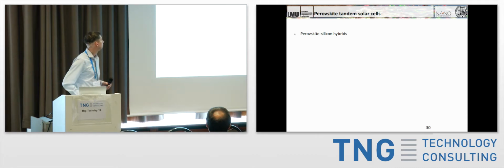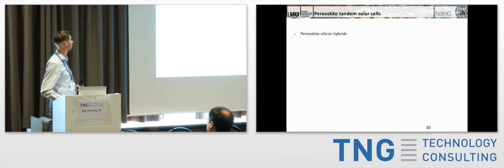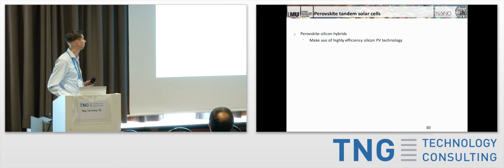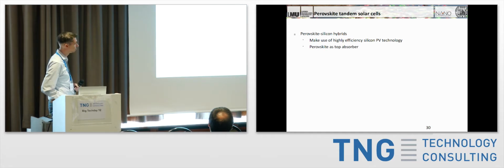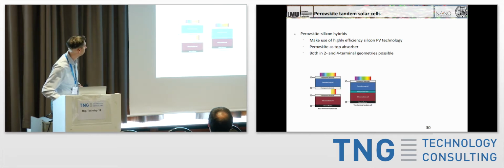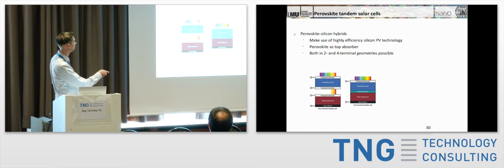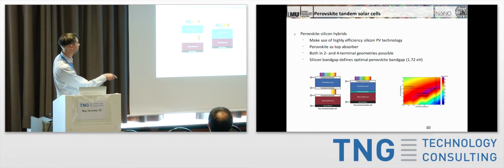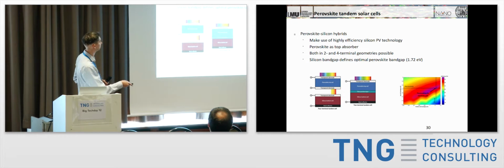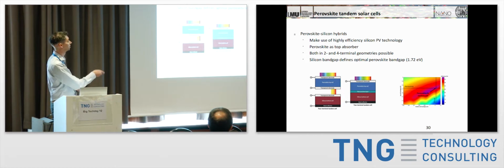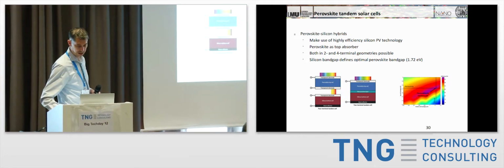All right. But possibly easier to achieve and quicker to commercialize are perovskite silicon hybrids. I mean, silicon's already been established for 40 years and is working quite efficiently. And so the idea is, why not make use of this highly efficient silicon PV technology and just put a second perovskite on top to absorb some of the light that the silicon can't use as efficiently. And so that's also possible in the 2- and 4-terminal geometries, so having the perovskite absorb light, only some of it passes through into the silicon. Then at the bottom, and that's again another one of these plots, just looking at for which energy you need. So essentially, because the band gap of silicon is fixed, that sets then the optimal range of the perovskite. So about 1.7, slightly shifted from the other case, but it is doable.